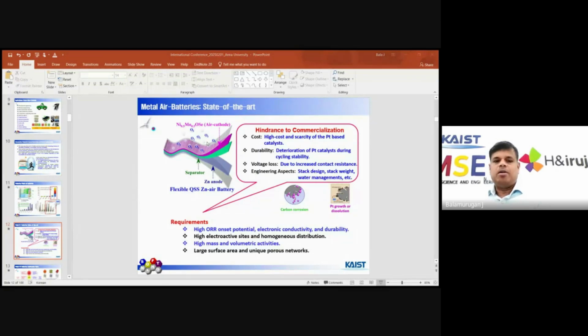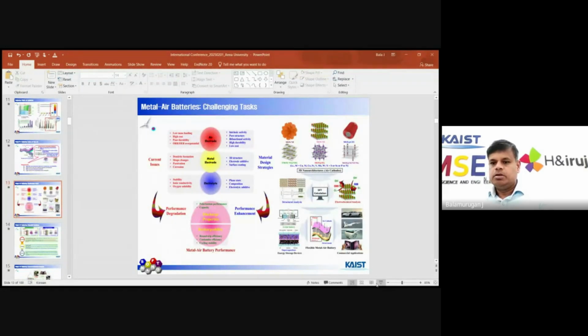So what is the problem of the zinc air battery or metal air battery? You can see when we use the metal air battery, the cost of the platinum-based catalyst in the ORR is very high. Another thing, with the electrode material, corrosion happens, because the activated carbon-supported platinum may be highly corrosive and may dissolve during the charge-discharge process. Therefore, we are using highly protective single-atom catalysts, or new strategies for making highly durable catalysts like core-shell or other types of materials.